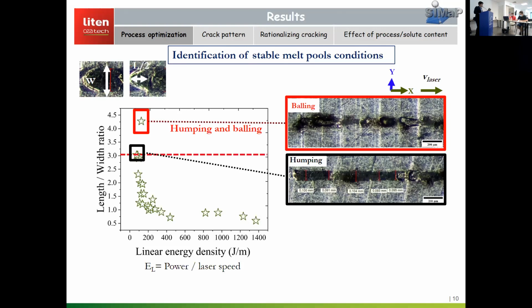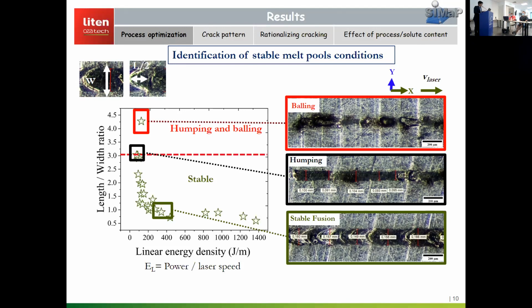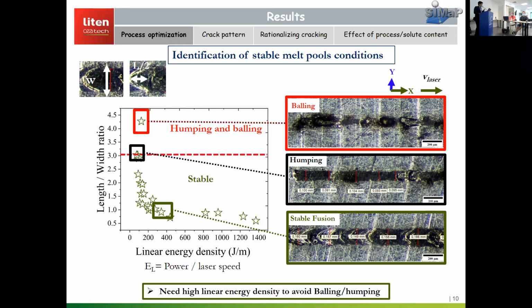So for low energy densities, for low power, high laser speeds, for example, we found two particular conditions, which are basically instabilities due to high speed. These instabilities are balling and humping. What is happening is when you have sufficiently high laser speed, you tend to disintegrate the melt pools in order to maintain the minimum capillary pressure inside the melt pool. If you have sufficiently high linear energy density, you can get a stable melt pool condition. For example, you have a continuous single track as shown in the green figure at the bottom. So in order to avoid balling and humping, we need a particularly high linear energy density.